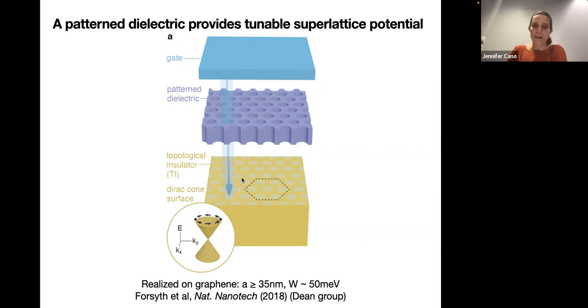a periodic potential. And I should mention that this idea of adding a periodic potential by this patterned dielectric was realized experimentally by Corey Dean's group in this neat 2018 paper. They did this on graphene. Just to throw some numbers out there, the lattice spacing, the unit cell of this pattern, they got as small as 35 nanometers, and the potential strength got up to 50 meV. So that's roughly the order of magnitude, which is state of the art.